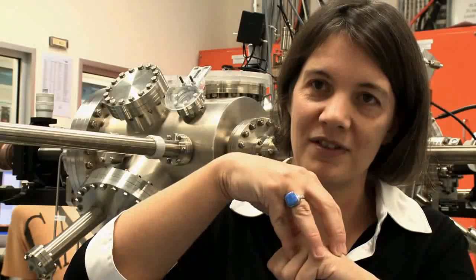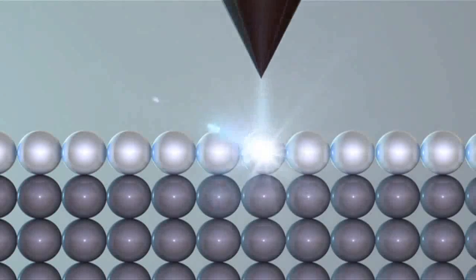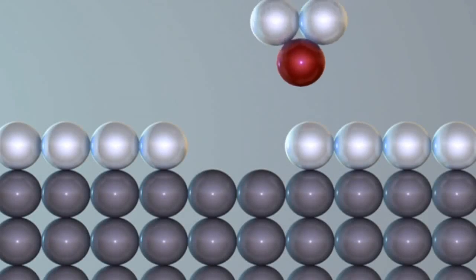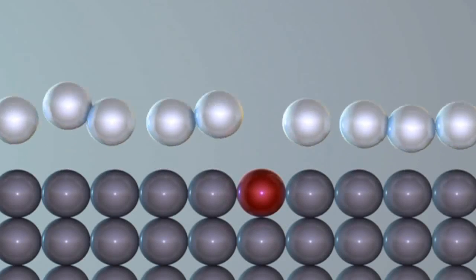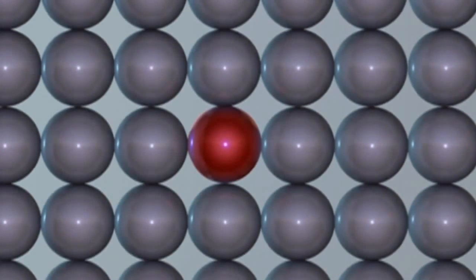And then by applying pulse voltages to the tip at certain points, you can actually change the chemistry of the surface. And typically what we do on the silicon surface is we take a silicon surface, nice and clean, and we put down one layer of hydrogen atoms. So it just literally has a silicon-hydrogen bond. And then with the STM technique, we can apply a voltage to the tip just above that silicon-hydrogen bond and literally release one hydrogen atom from the surface, leaving a dangling bond. And that's very reactive. And to that reactive dangling bond, we bring in phosphine gas, which will only stick to that dangling bond and nowhere else on the surface. And it's in such a way that we can bring that phosphorous and put it exactly in the one atomic lattice spacing of where we want it. And then once we've done that, we encapsulate with silicon over the top of it. And by encapsulating with silicon, we surround it with silicon atoms. So it's sitting one phosphorous atom, silicon all the way around it. It's a nice, clean environment for that phosphorous atom.